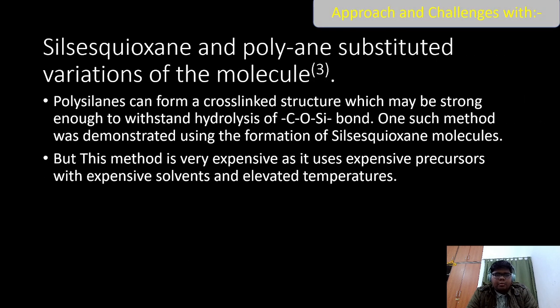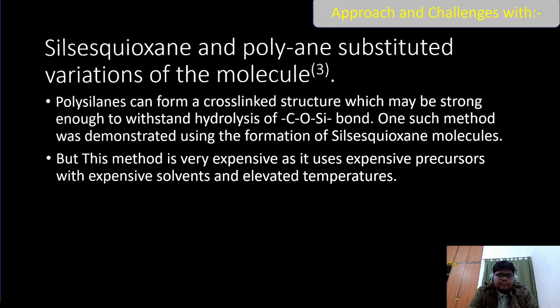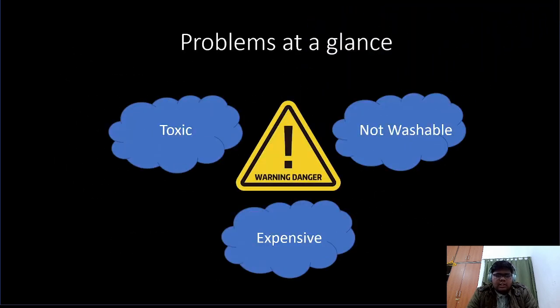Another interesting approach has been use of silsesquioxane and polysilane substituted variations of molecule. Polysilanes can form cross-linked structure which may be strong enough to withstand hydrolysis of C-O-Si bond. One such method was demonstrated using formation of silsesquioxane molecule. But this method is very expensive as it uses expensive precursors, expensive solvents, and elevated temperatures. So to see the problems at a glance, the current formulations are toxic, not washable, and expensive.